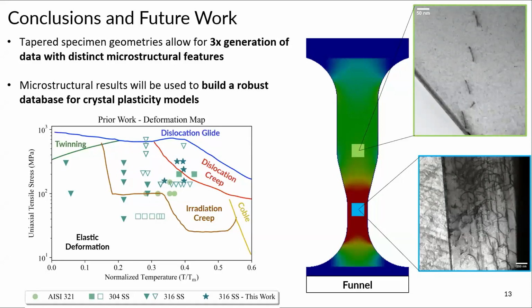So in conclusion, with these geometries, we can generate about 3 times the amount of data in one experiment, which therefore accelerates finding all of these mechanisms out. And then these microstructural results are being used to build a robust database for crystal plasticity models. So crystal plasticity is the stress-strain relationship in your crystal. And so if we know what happens on a microstructural level, like density, size, orientation, it can help build these models and therefore predict at what point this material fails.